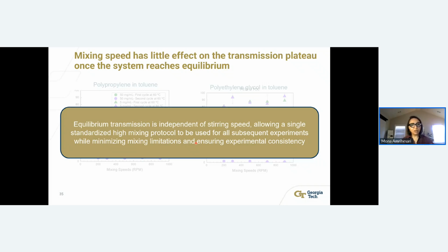Since we are dealing with large molecules, we kept a higher mixing speed to facilitate the agitation of the polymer and avoid gelation and other complications that might happen as the dissolution is happening.